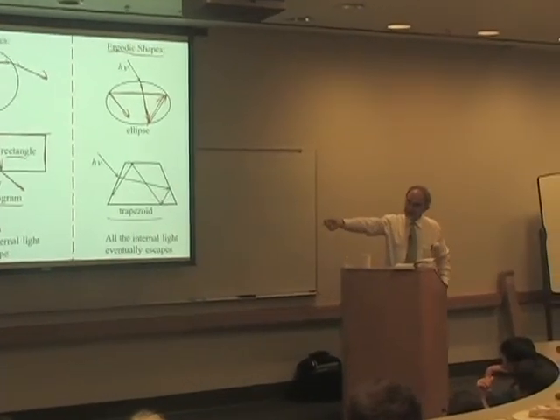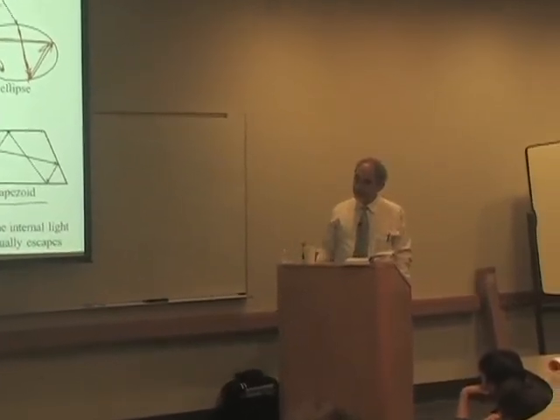If I take a glass ashtray that has a very artistic shape to it, and I'm standing out in the parking lot, that will have maybe 10 suns, maybe more if it has a higher index. So there's a huge qualitative difference, geometrical, and if you just break the plane parallel symmetry, you get a tremendous internal concentration of sunlight. That's kind of amazing, because the refractive index is really high for semiconductors, so it makes a huge difference. So it's this 4n squared factor. So where did it come from?